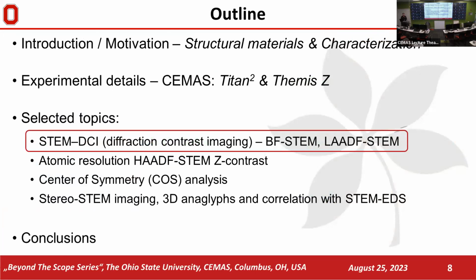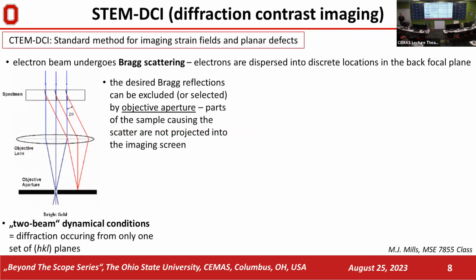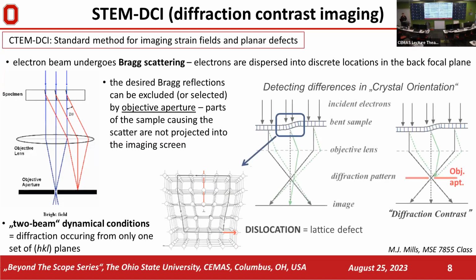So let's talk about diffraction contrast imaging. We know diffraction contrast imaging as one of the oldest and established methods for imaging strain fields of planar defects in conventional TEM. We know it's based on Bragg scattering of electrons which are scattered from non-perfect parts of the crystal. And then we can use an objective aperture to create a contrast. One of the types of defects which we investigate is dislocation. Usually in conventional TEM, we work in two-beam dynamical conditions where diffraction is occurring only from one set of HKL planes.